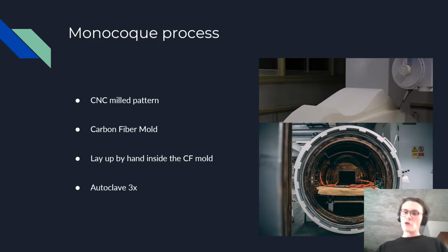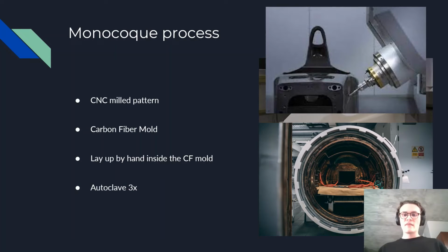Oftentimes the teams will have to go in and trim some parts, maybe sand here and there to make it extra smooth, but that is the basic process. And in the end, what oftentimes does happen is it has to go through another milling cycle. This is needed because precise location on the layup is oftentimes hard to define in the layup schedule. For that reason, after laying it up fully and curing the part fully, it is taken into a mill, which then oftentimes defines the locating features. For example, the suspension hard points, where the engine attaches, and so on.